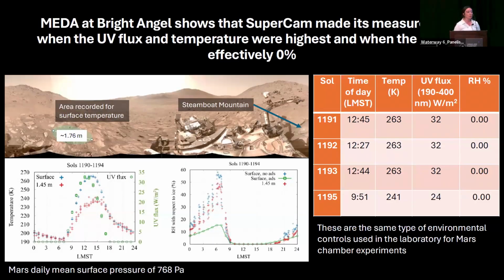Another interesting thing that we discovered by comparing the atmospheric data to the SuperCam data, based on the times that we do these measurements on Mars, is that we do it during the time when the temperature is highest and the UV radiation fluxes are high, so we can see it's 32 watts per meter squared for this time on Mars during the experiment, and that we're doing it during the time of lowest relative humidity. And this range here is the range of when SuperCam performs its experiments on Mars.